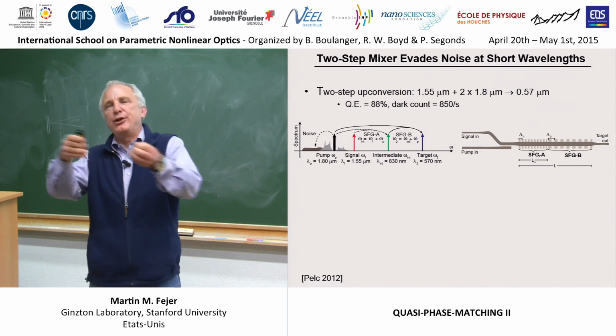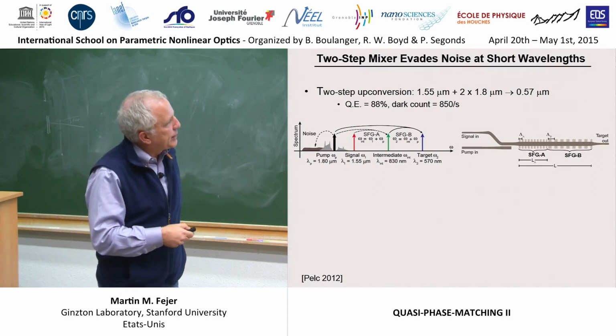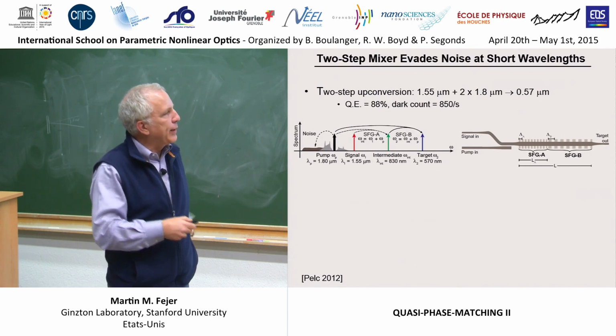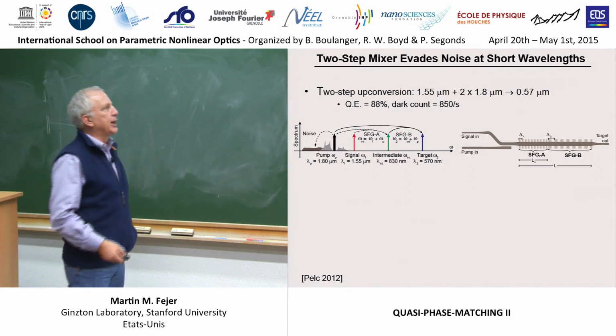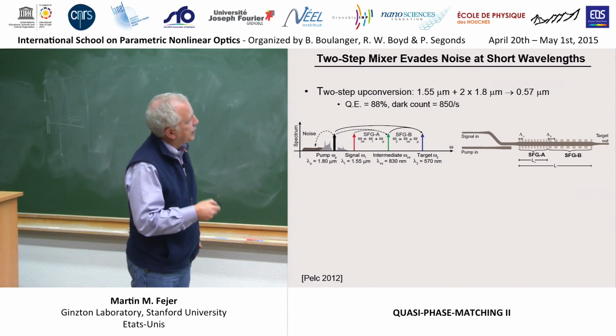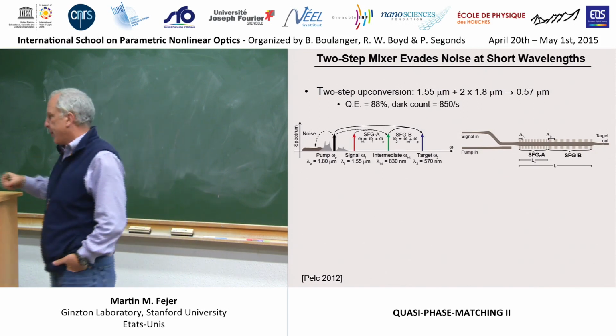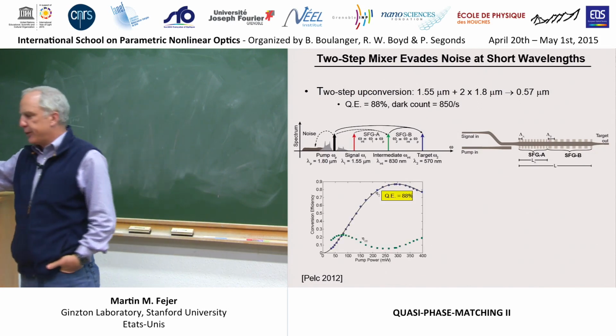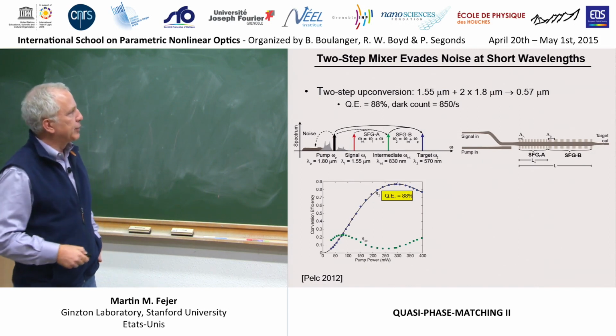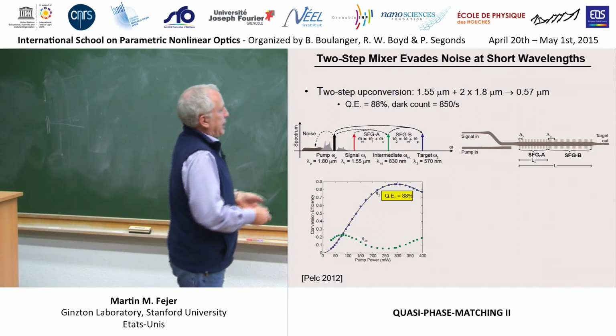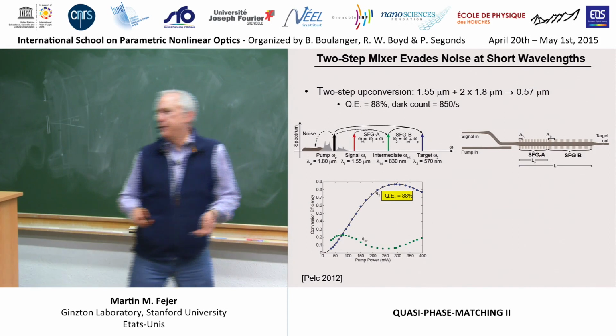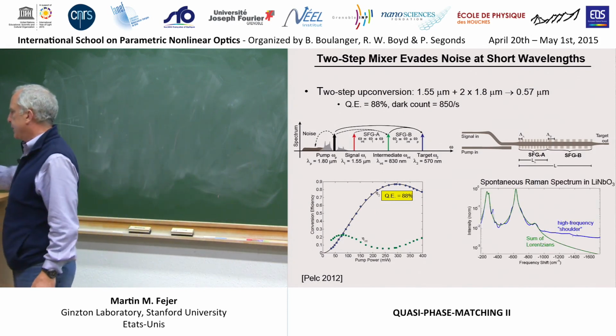And of course, it's easy to do two sequential mixing processes. You just put two different QPM gratings in your waveguide, and you have two different mixing processes. And so you can integrate this structure quite easily. And when you do that, you end up with a quantum efficiency of about 90%, and the dark counts were a few hundred.